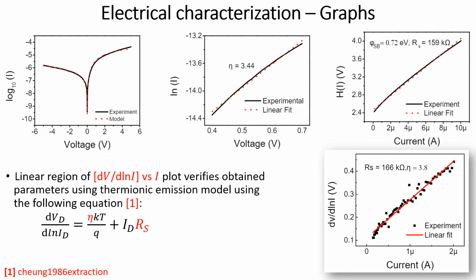We have also verified the results that we obtained using the dV by d ln I versus I graph. The equation which we have obtained from H(I) is manipulated to obtain the following equation. From this plot, we obtain the eta value as 3.8, which is closely correlated to the previous eta we got from the thermionic emission model, that is 3.44. Also, the series resistance doesn't change by a huge margin. The series resistance obtained by this verification method is 166 kilo ohm, while we obtain the series resistance of 159 kilo ohm via the thermionic emission model.